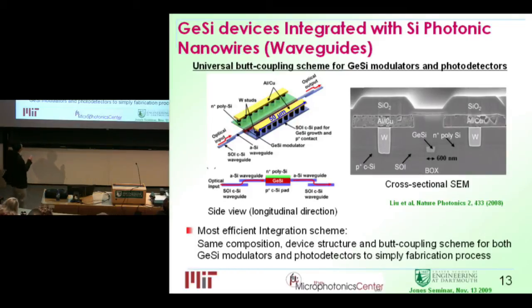So in terms of device structure, we're thinking a universal scheme for both detectors and modulators that are coupled with this silicon nanowires. This is a schematic 3D representation. So the light can couple from a crystal silicon layer into an amorphous silicon layer. The reason why we do this coupling is that the amorphous silicon still tends to have more loss than perfect crystalline silicon. So we want to minimize this length. And then it couples to a piece of germanium longitudinally. When this piece of germanium is short enough, it's relatively transparent to the light. So when you apply the bias, you turn this material from transparent to opaque at a certain wavelength. Then you can perform modulation.